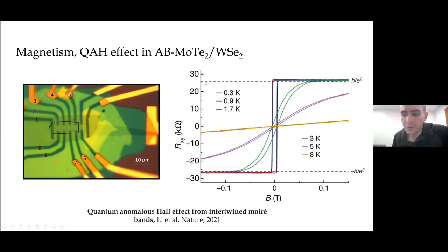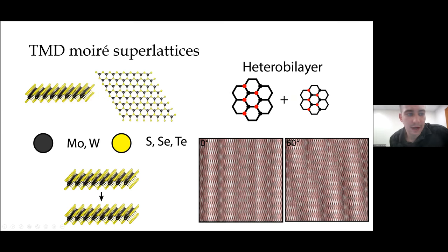So this is also different from the previous systems that I've discussed in that it isn't graphene. It's based on these transition metal dichalcogenide systems. So these have a bunch of heavy transition metals bonded to chalcogenides and together form the lattice shown here. Another difference is that in twisted bilayer, one of the interesting things that you can do with a pair of graphene lattices is treat the twist angle as a variational parameter to minimize bandwidth. That's not what's going on here. The bandwidth is set entirely by the properties of the system. The goal here is to align the lattices with each other and realize a heterobilayer moiré superlattice. So have two different lattices that are aligned with each other and thereby realize a moiré superlattice.